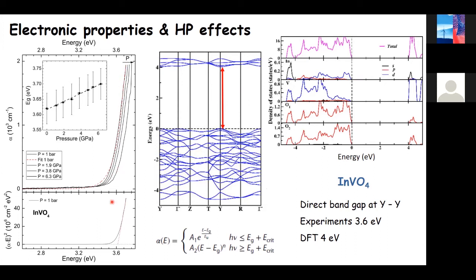This one, you can see here better, is the one at 1 bar pressure. We have here a very sharp absorption, which indicates a direct band gap. And you have here an absorption tail, which is what I told you, the Urbach tail. Indeed, if you use this model, which is a direct band gap plus the Urbach tail, you can explain our absorption very well. This is done here, where we compare this black solid line with this red dashed line. The red dashed line is the model. So this way we have determined the band gap energy as a function of pressure.